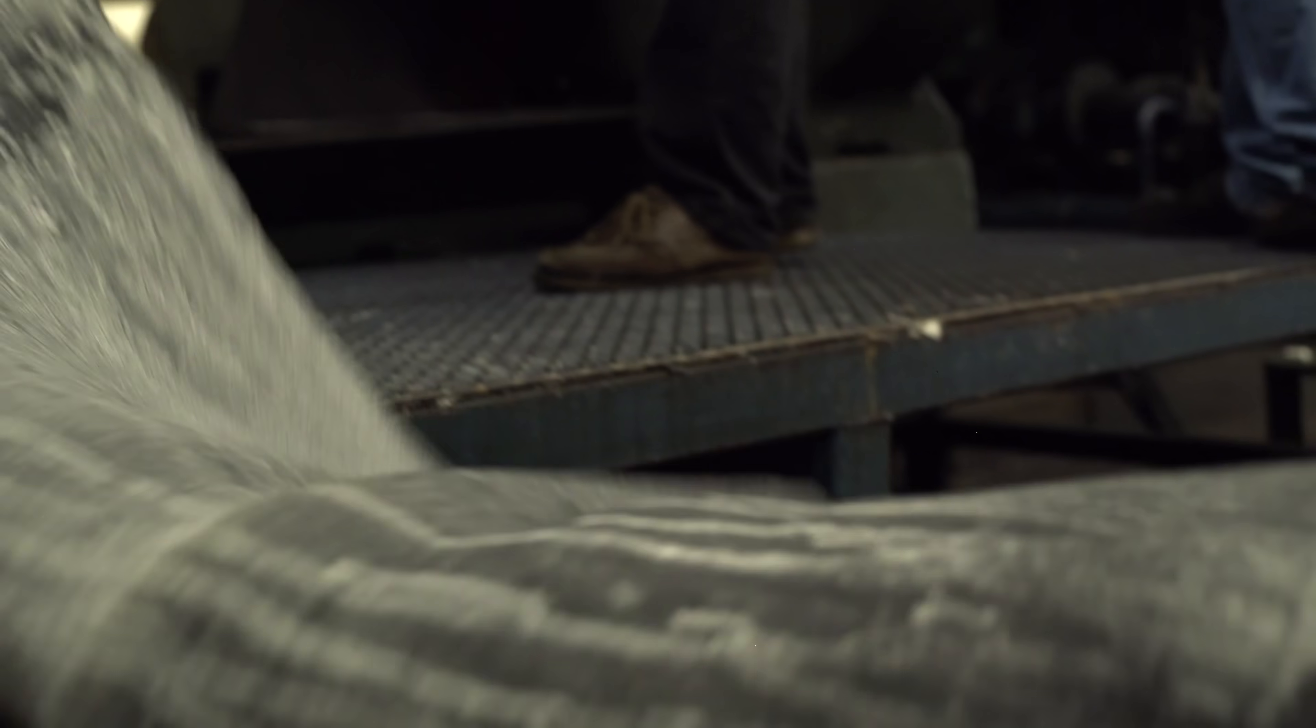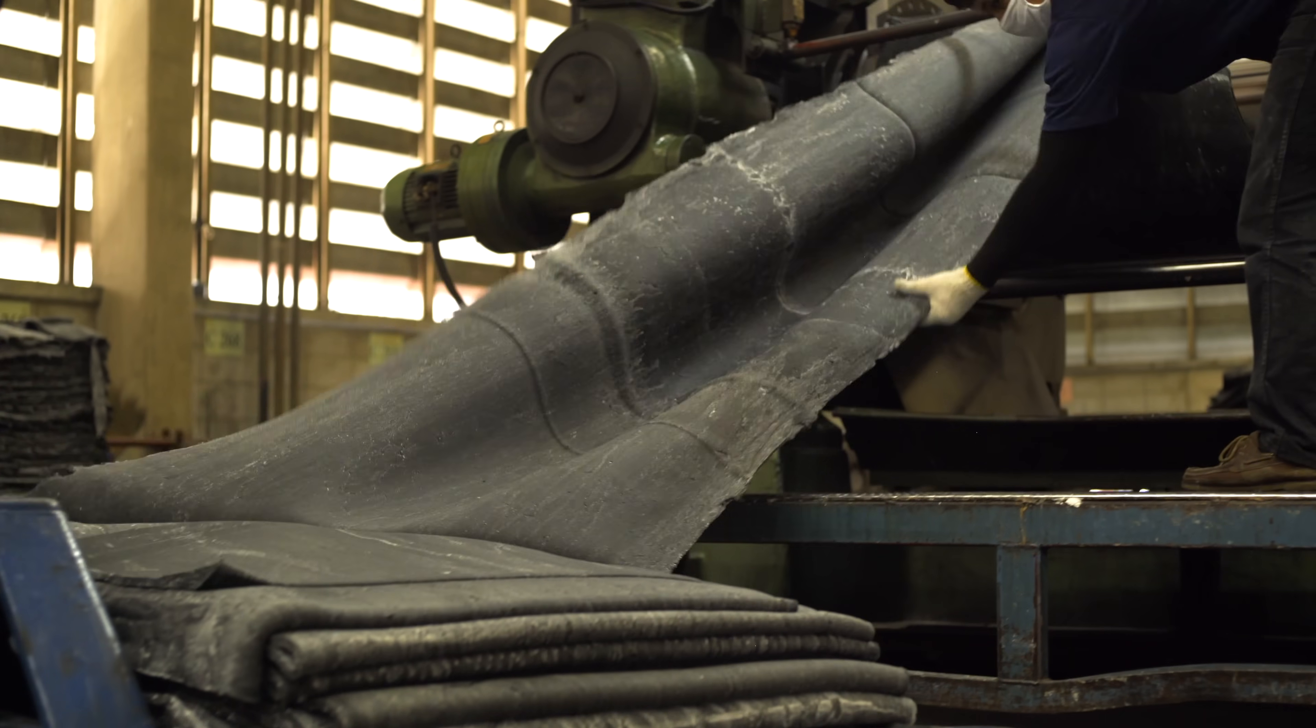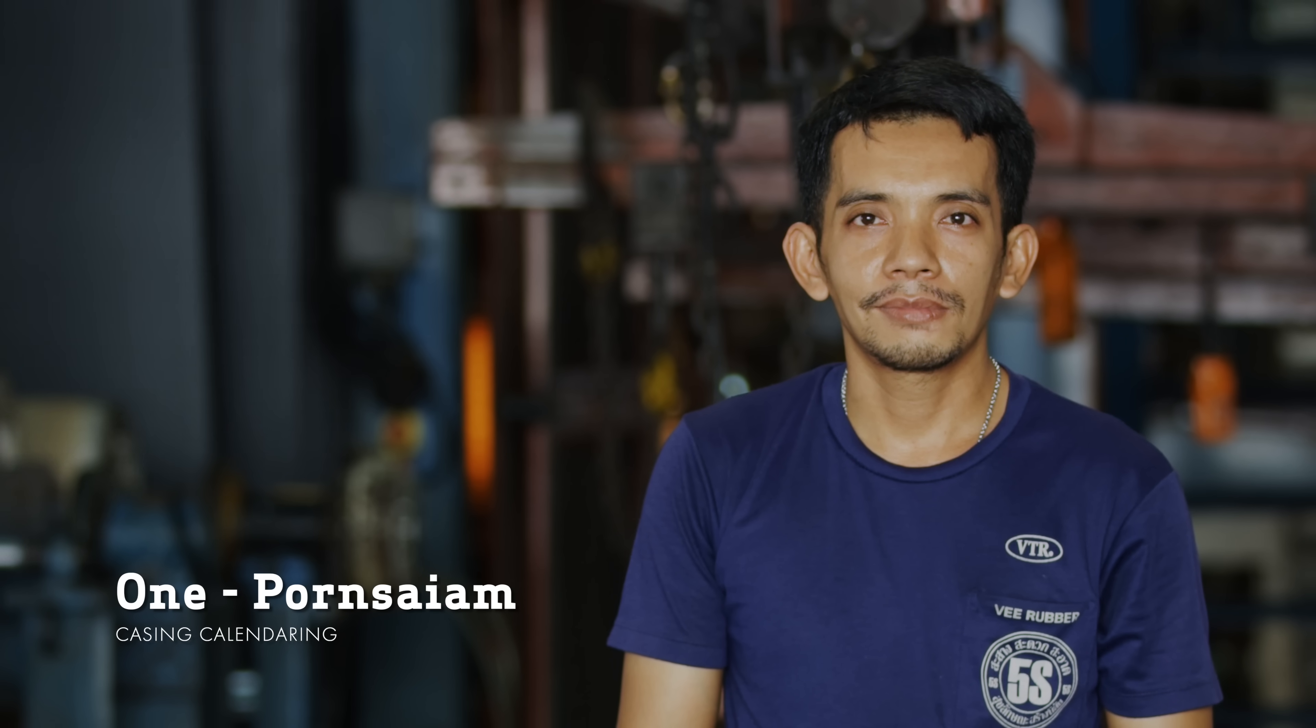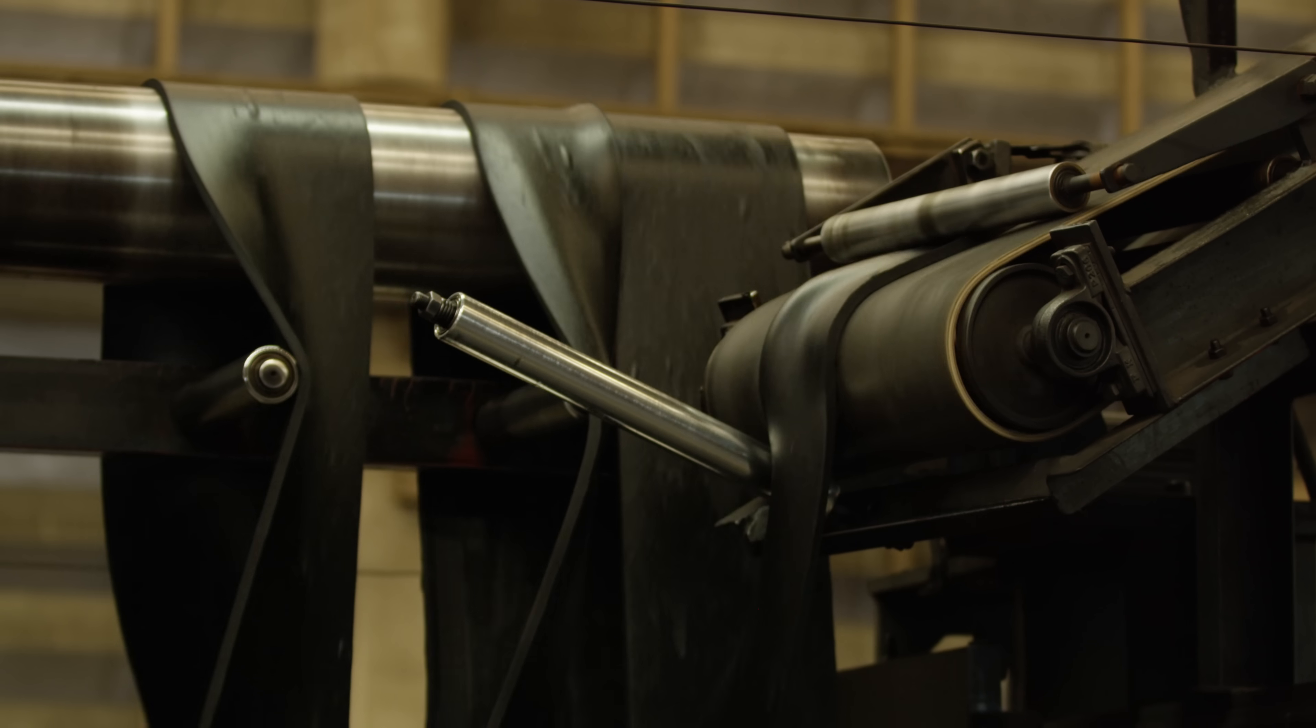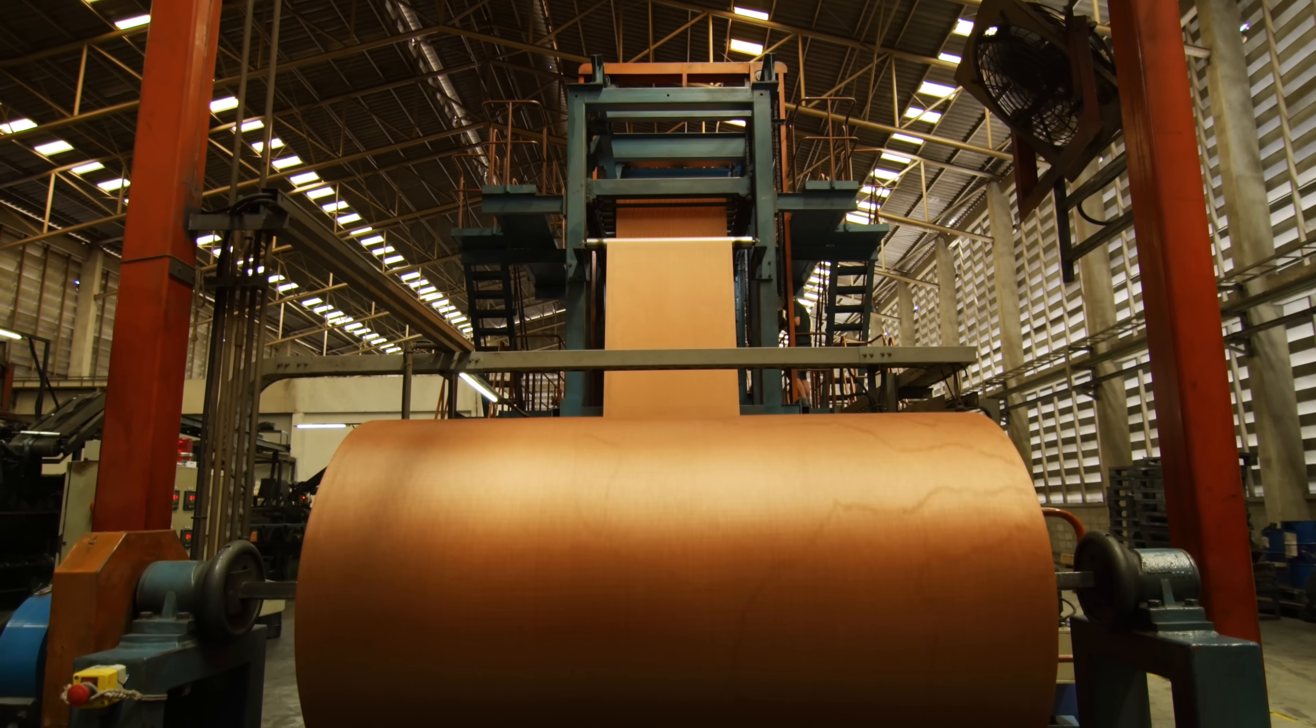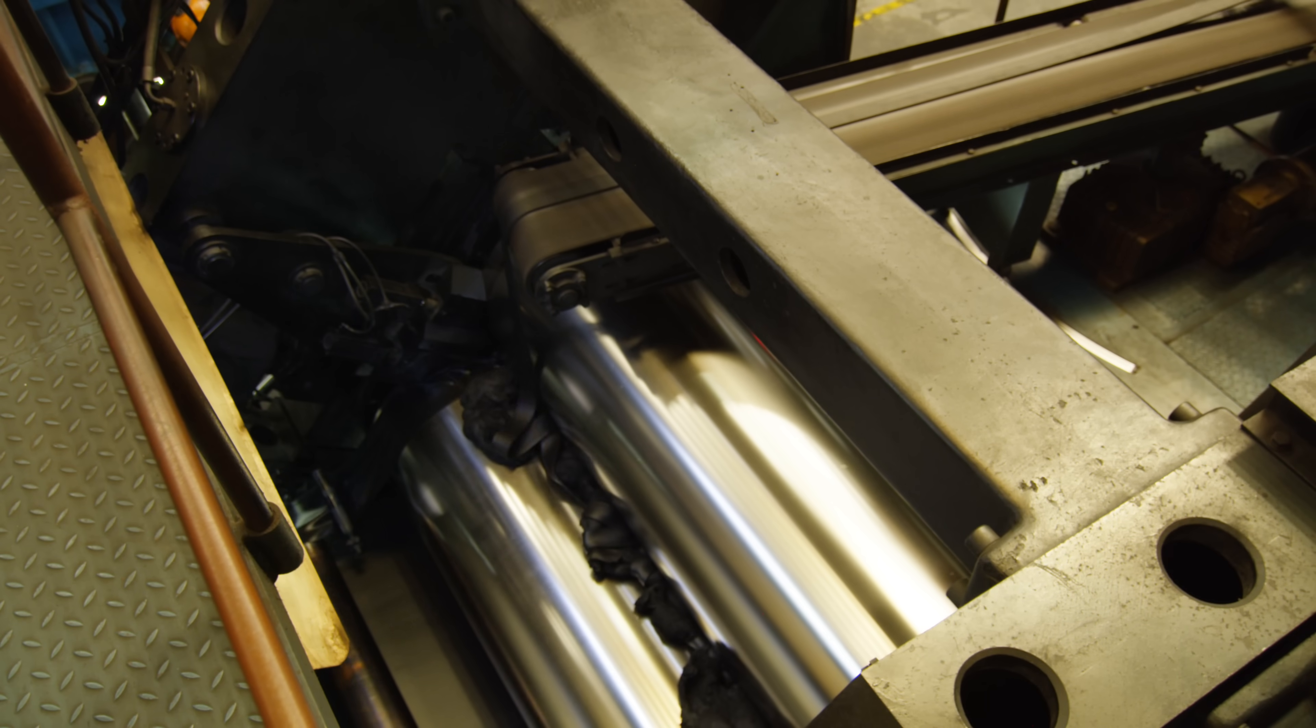After the rubber blocks are heated and extruded into belts, they make their way to calendaring, an extensive task that involves as many as seven employees, including One Pornsaiam. During this process, the rubber compound is rolled to a thickness of 0.2 to 0.4 mm before being fused with nylon threads for structure, creating a ply that will become tire casings.